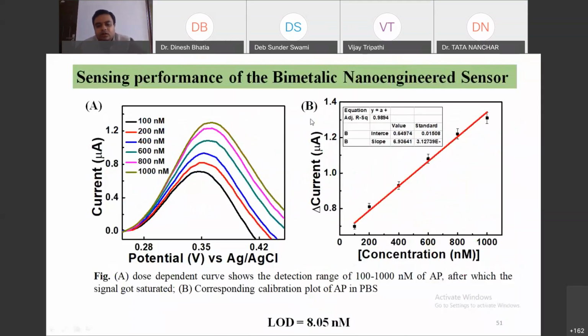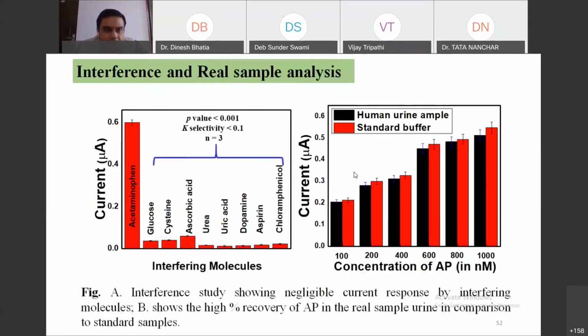After this, we checked the response of acetaminophen in this case. Acetaminophen is the target molecule. As we kept increasing the concentration of acetaminophen, the signal kept increasing between 100 and 1000 nanomoles, and this is a straight calibration plot which shows a limit of detection of 8 nanomoles, very low actually. So this is the interference data where you can see the closely related compounds which coexist with the acetaminophen.